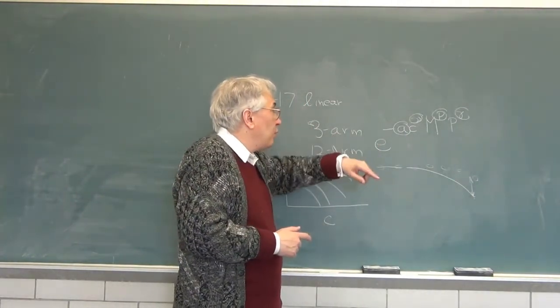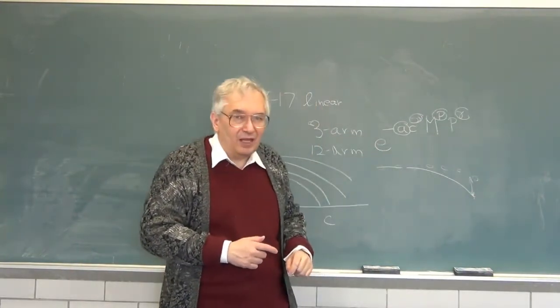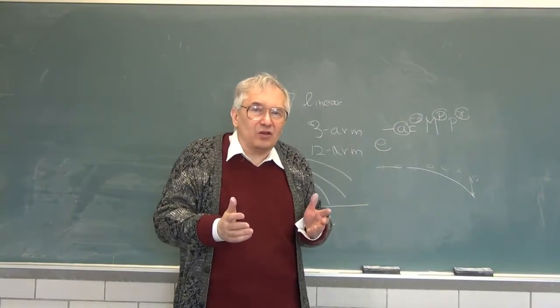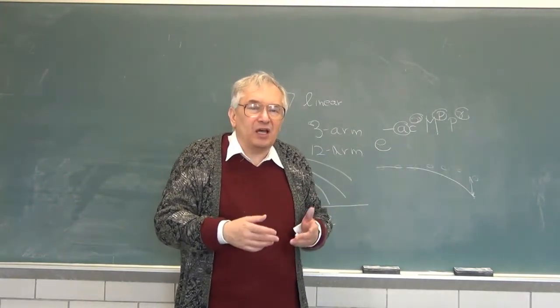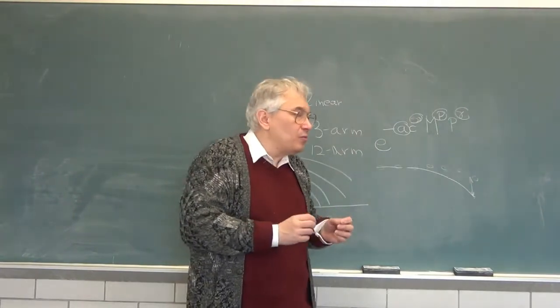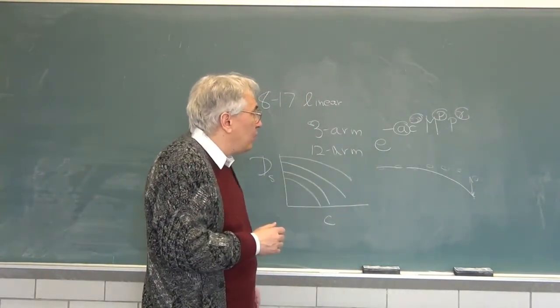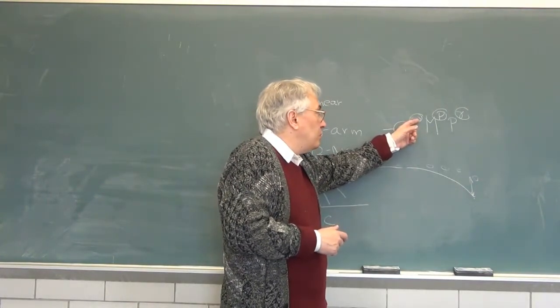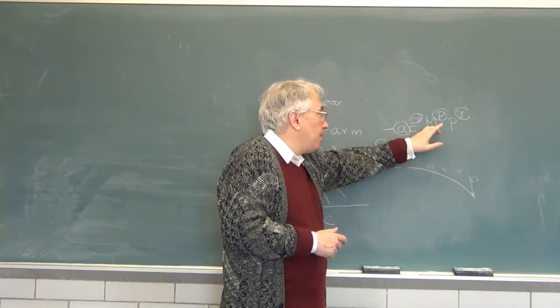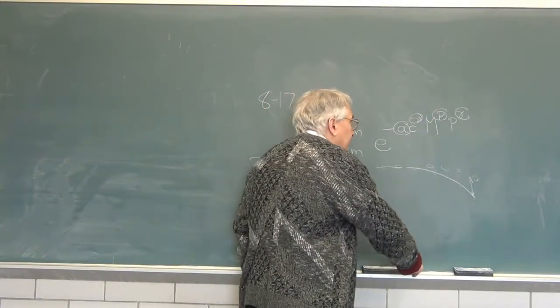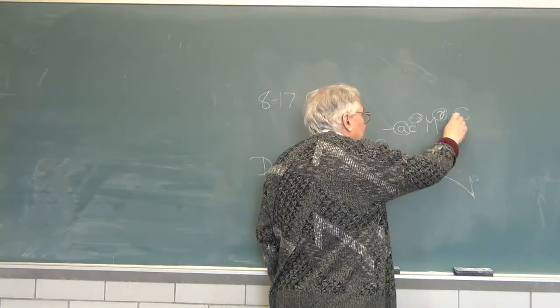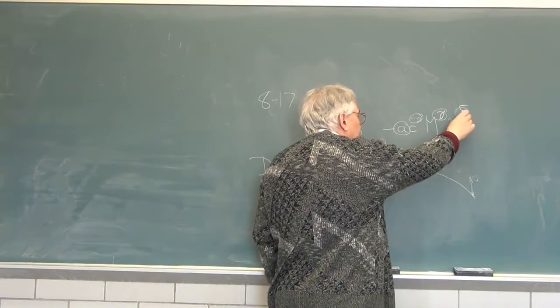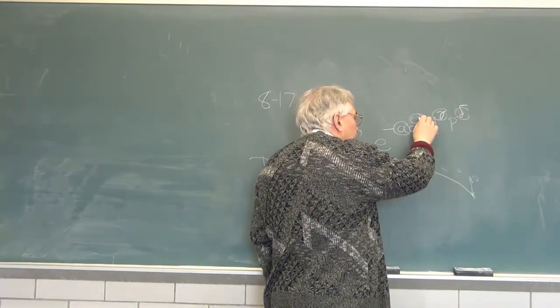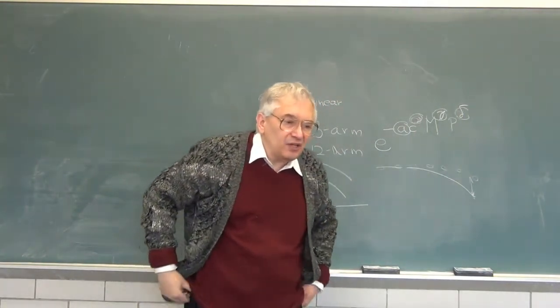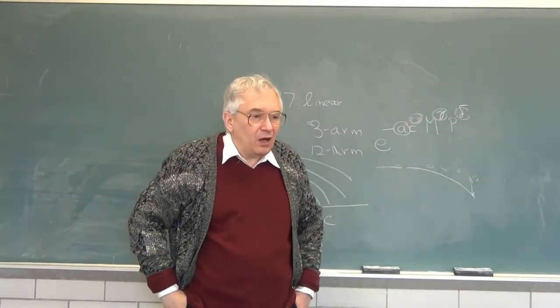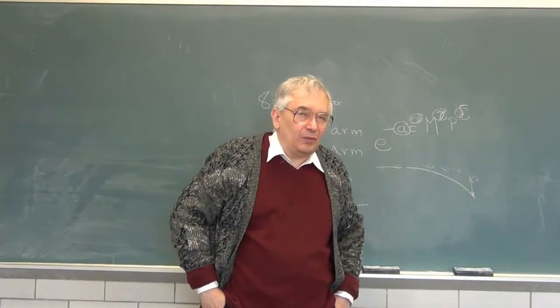Well, the fitting form that was used just took nu to be a constant. And saying nu is a constant rather than some well-defined function of probe size is not quite good enough an approximation for very small probes. If you wanted to go to the next step, you would have to put in that nu is some function of... I got the exponents wrong. I usually say gamma and delta. M to the gamma, P to the delta, and nu in the graphs is being treated as a constant. Well, it's an approximation. Okay, well, that's very nice for linear polymers.